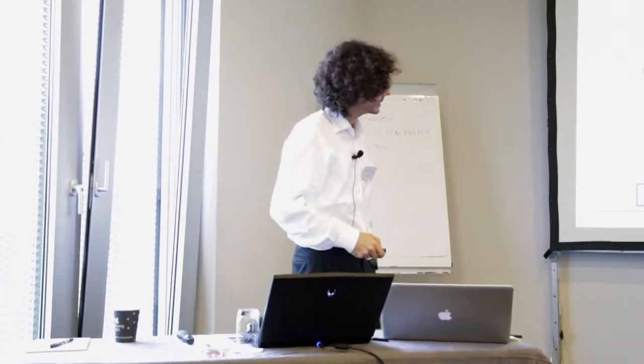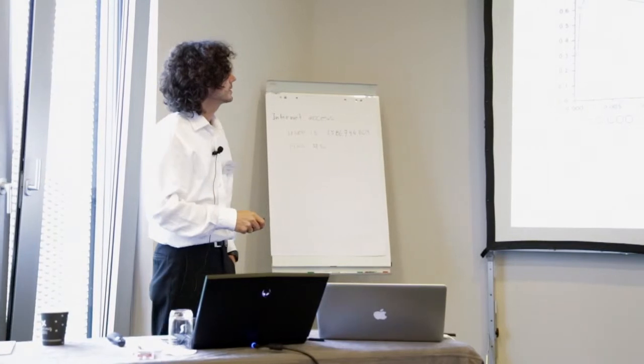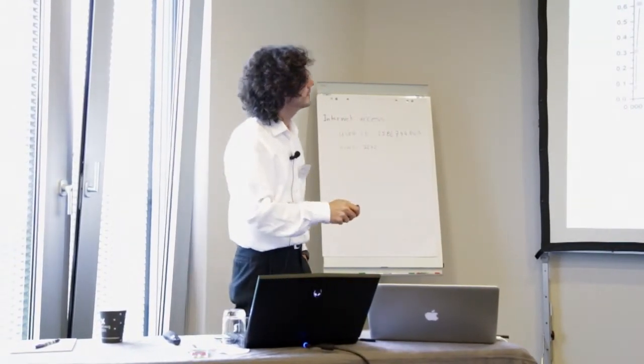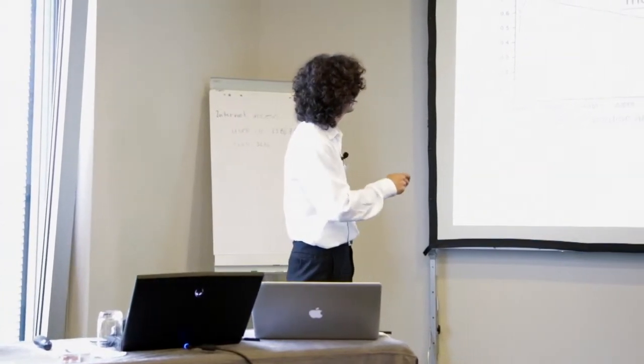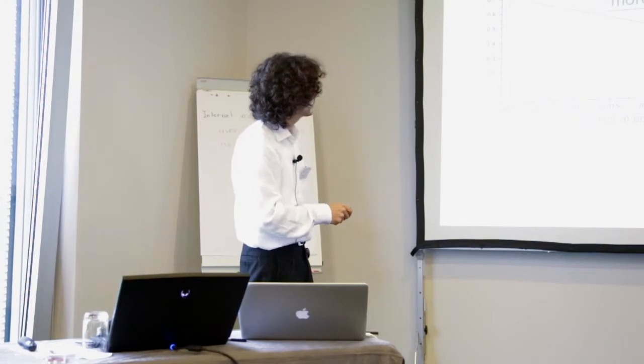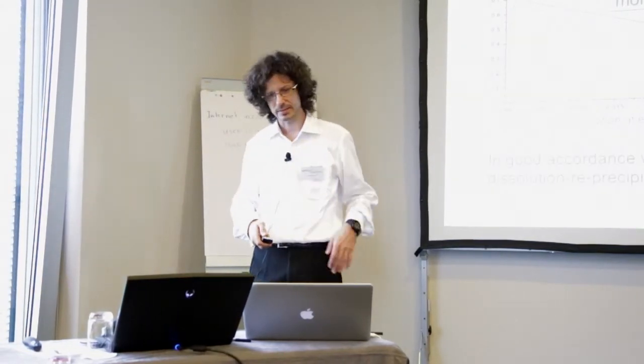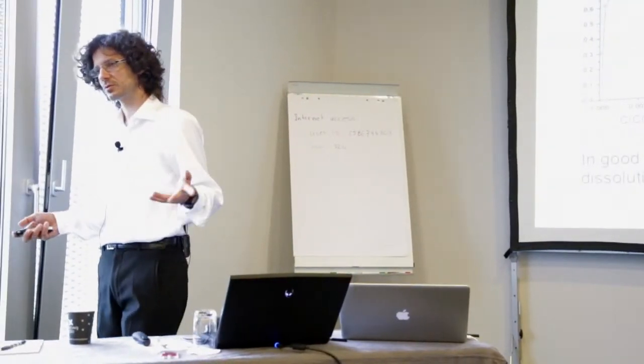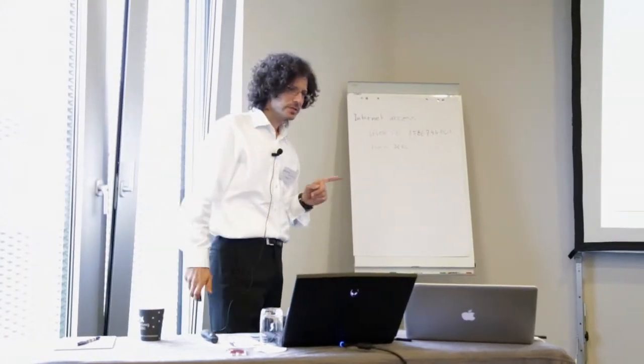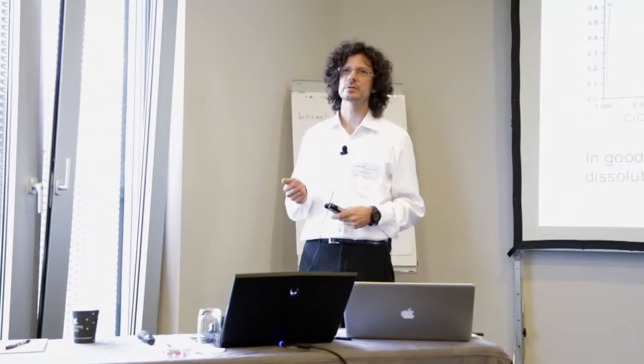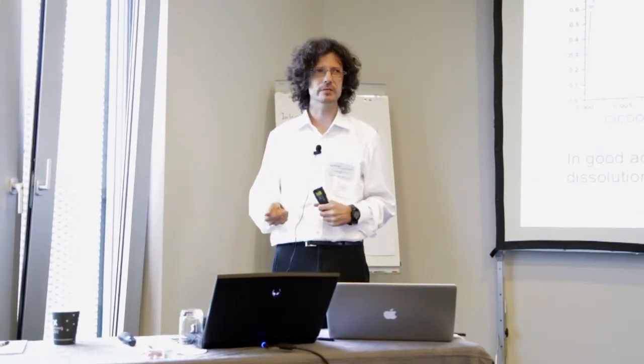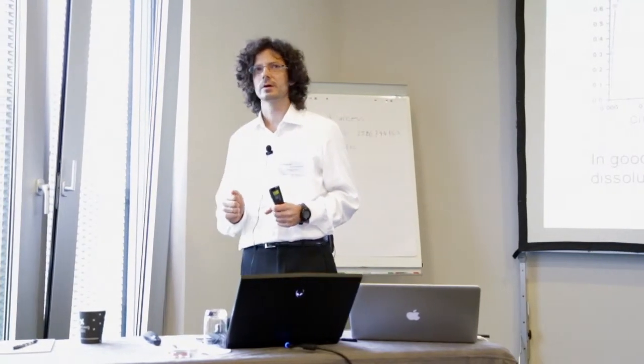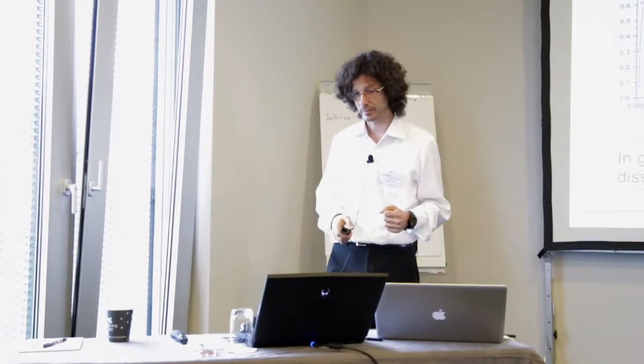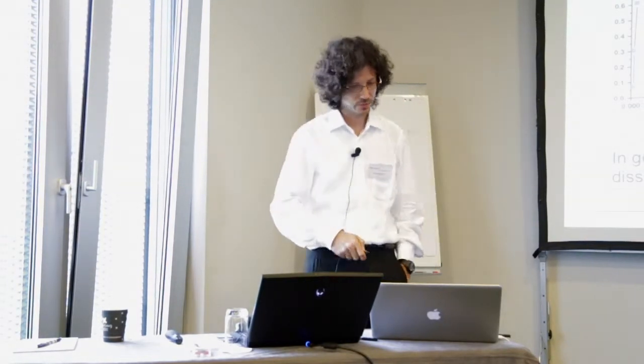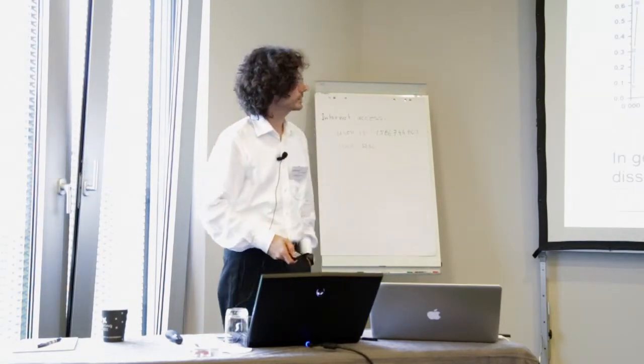That is an important learning, and if you look at the incorporation of the polymer in the AFm phase, you have this very non-trivial consumption of the polymer, which also suggests that we're facing a non-trivial behavior which is not just one of adsorption and plateau. So the teachings here, again, are that these polymers have a strong effect on the reactivity of the aluminate phases, on the nucleation and probably growth of these phases as AFm or monosulfate and also ettringite. So I think that's another of the broader reaching results of this PhD, which I think has not yet been fully realized.